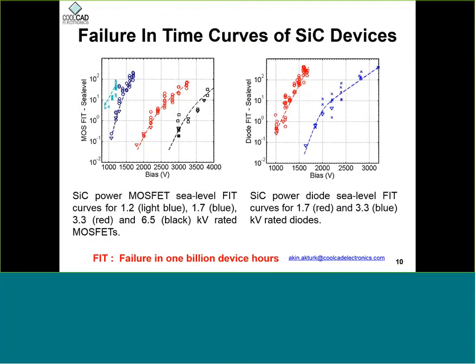So after we measure failure cross sections, that is, to measure it, we write down how many neutrons it takes to fail a device within a set of devices, and we either wait until enough devices fail or a large neutron fluence is reached. A large neutron fluence means in the actual application, it would take a very long time to reach that level. So then, using those data points, we calculate failure in time curves. And failure in time is defined as the failures in 1 billion device hours. So if you have a FIT of 1, you'll have 1 device fail on average every billion hours.